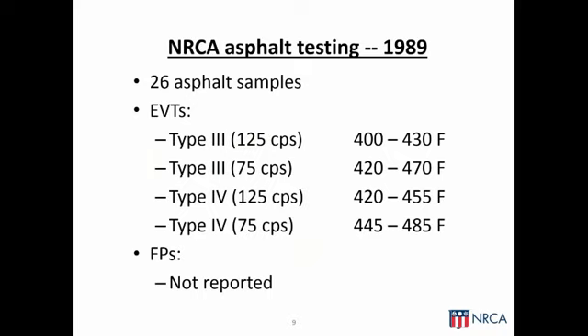And in '89, NRCA and Bill Cullen collected 26 asphalt samples, and the asphalt was tested for its equiviscous temperature, or in other words, its preferred application temperature. And you can see the values on the screen in front of you. To give you a little bit of perspective, back probably about 8 or 10 years before this study, I actually spent some time as a roofing mechanic, actually doing roofing work and mopping and things along that line. And in the 82, 83 time frame, we were looking at EVT temperatures for Type 3 asphalt somewhere in the range of about 375 to about 390 degrees Fahrenheit. So the point to be made is, over time, up till 1989, we saw a slight creep in EVT temperatures upwards. So that's a baseline point, as I mentioned.